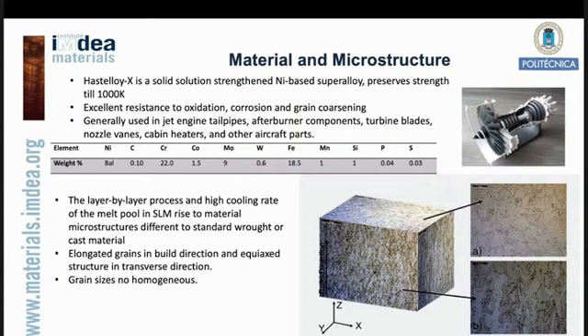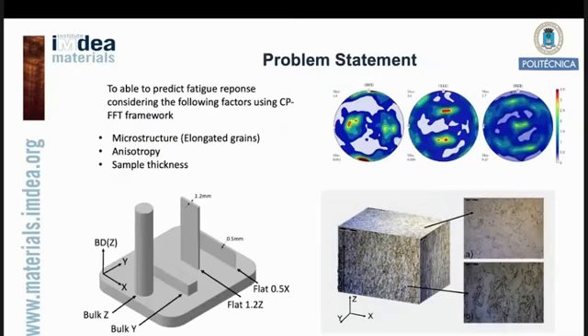This non-homogeneous grain size structure will lead to an anisotropic response, and it is detrimental to fatigue life. So this is the problem statement: because we have samples with different grain microstructures and anisotropy, we should have a model able to predict the fatigue response, considering the CPFFT framework.